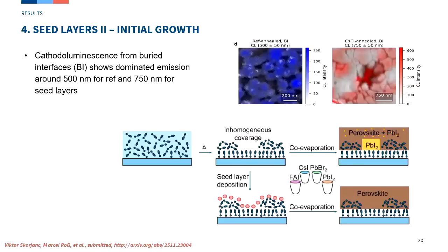It gets a bit trickier in terms of the measurement, but what you see here is the emission of the perovskite from that buried interface. What we do is first evaporate the perovskite, then rip it apart and peel off the perovskite, and in the electron microscope look at the cathodoluminescence emission in a filtered way. You see a lot of blue for no seed layer, and you see the true emission for the one that has the seed layer.